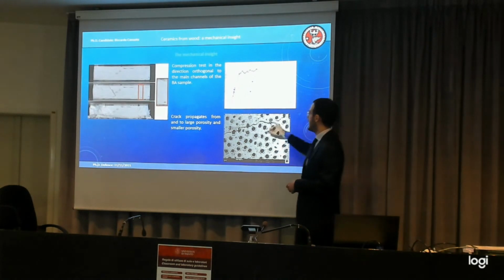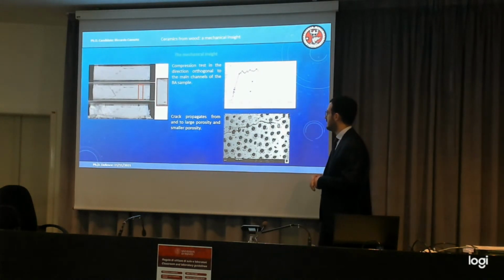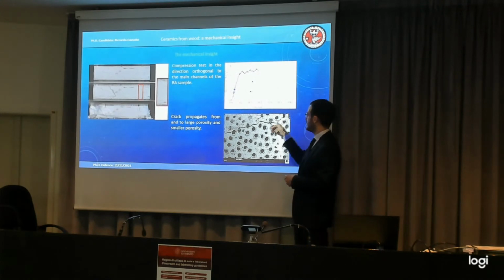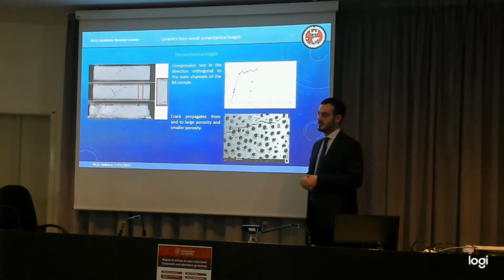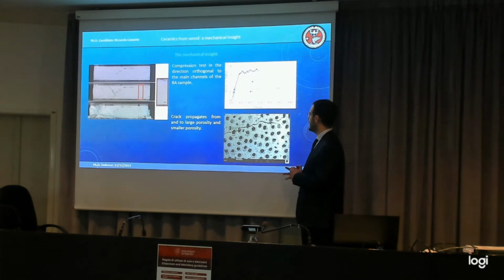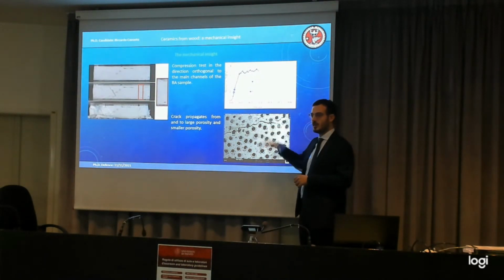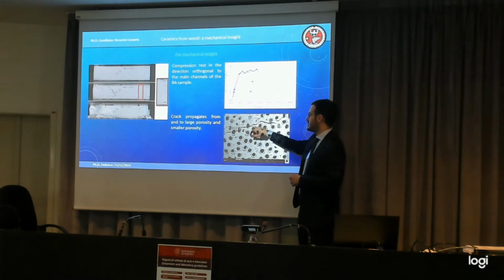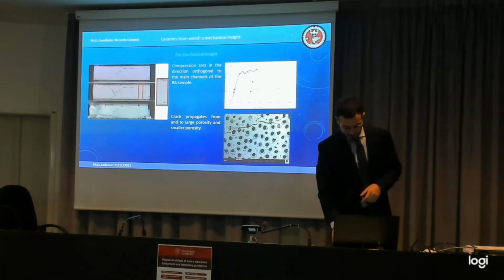And this is a nice picture obtained from SEM of a crack propagating through the sample. We can see that the crack is actually developing and passing through larger voids, but as we will see in a few minutes, smaller voids have a huge impact.